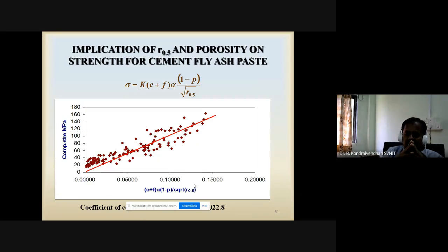So here we already established the relation between the pore distribution parameter and the strength in case of OPC. Here we slightly modified it. Instead of only using the C, we are adding the F also. That's how the formula becomes sigma equal to K into C plus F. Okay, instead of C, I am using C plus F. Remaining things are the same as the previous one.